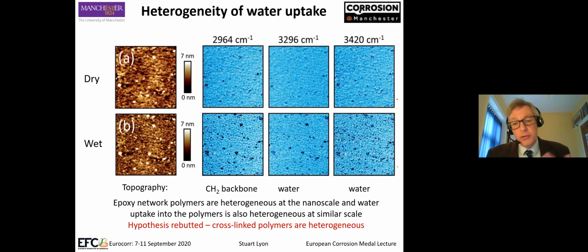So following on from that, should we expect water uptake to be chemically heterogeneous as well? And that is in fact correct. We can see these nodules coincide with increased methylene groups, so higher polymer activity, and they're also associated with increased water uptake. So epoxy network polymers are heterogeneous at the nanoscale, and water uptake into polymers is also heterogeneous at a similar micron scale. So we rebut the hypothesis that cross-linked polymers are homogeneous. They are in fact heterogeneous.